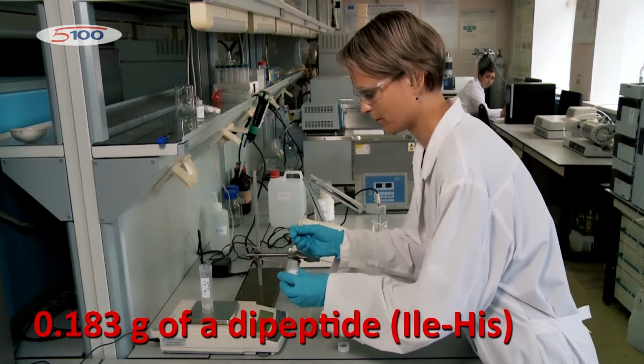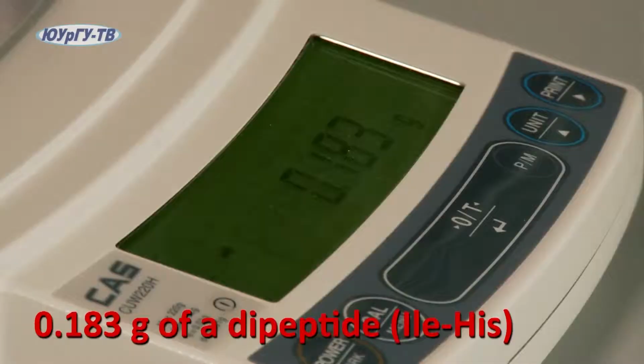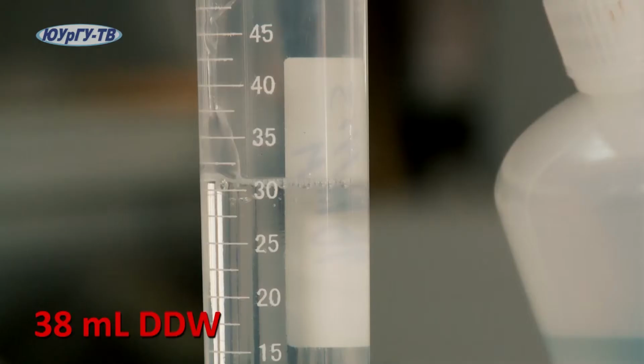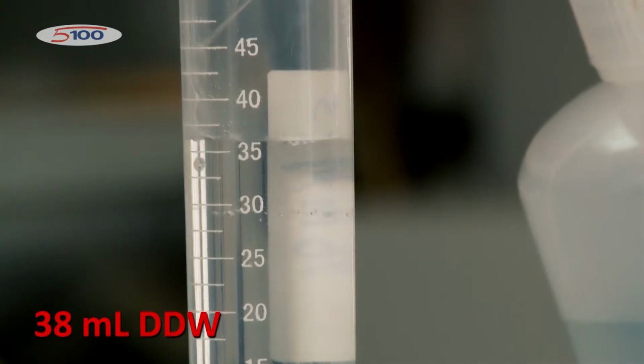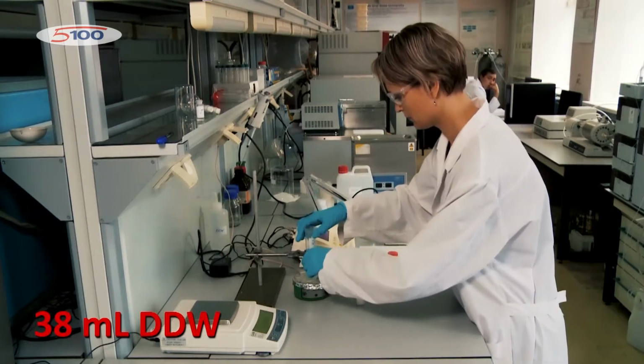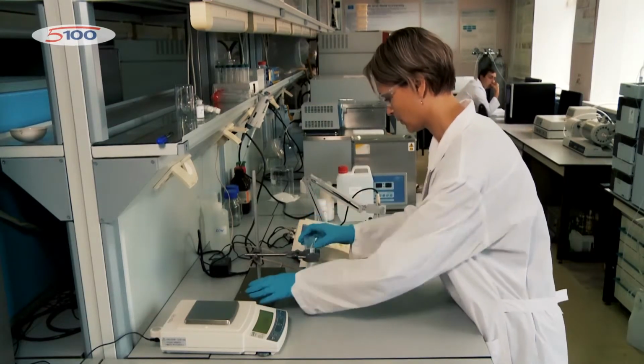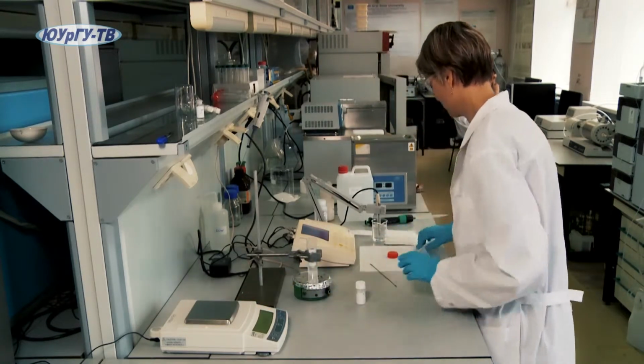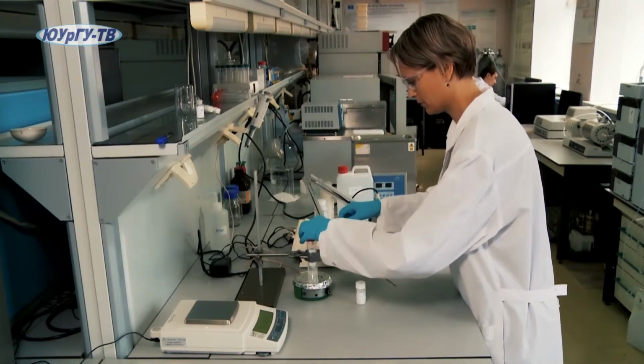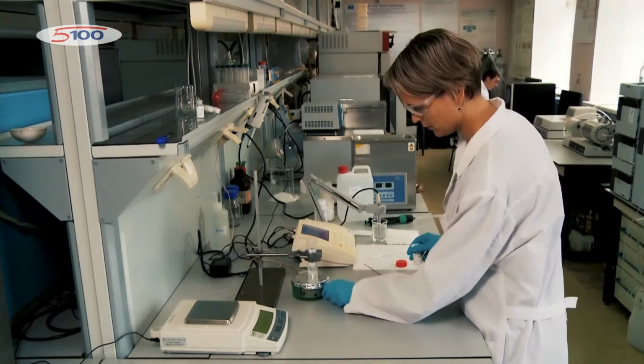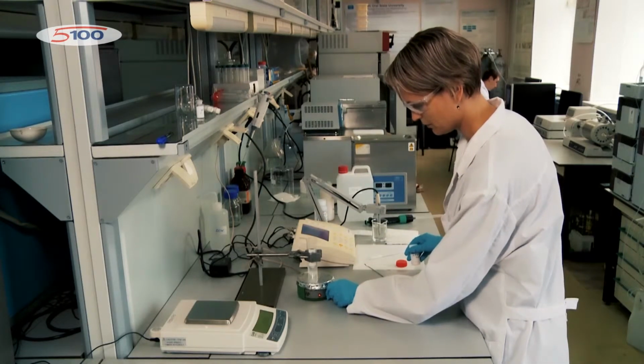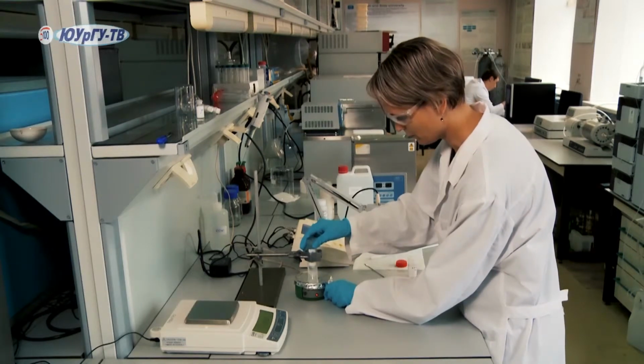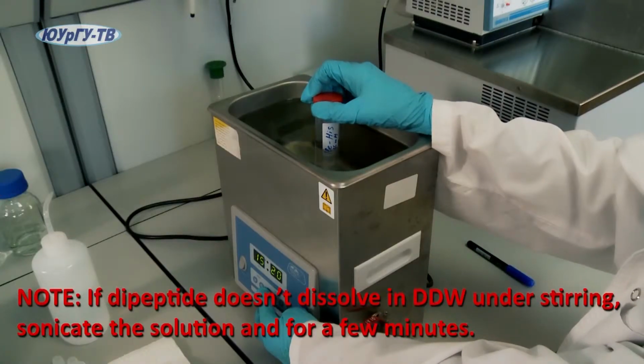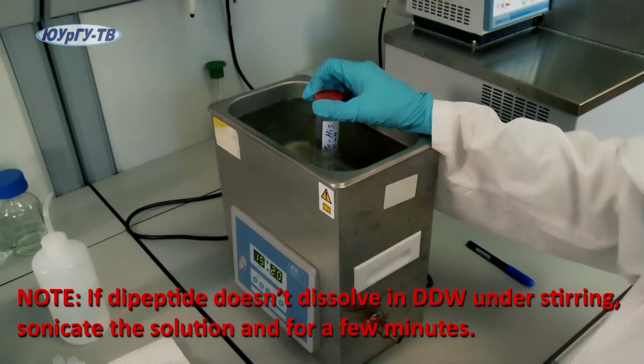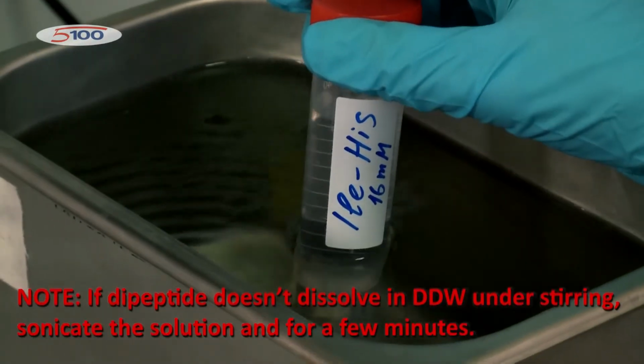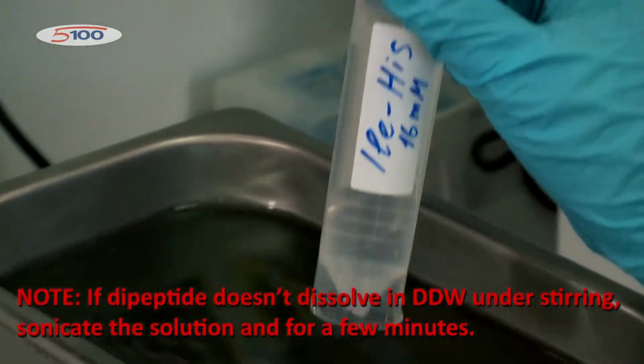Place 183 mg of dipeptide in the sterile polymeric test tube and dilute up to 38 ml with double distilled water and dissolve at room temperature under vigorous stirring. If the dipeptide doesn't dissolve in double distilled water under stirring, place the dipeptide solution into the ultrasonic bath and sonicate for a few minutes.